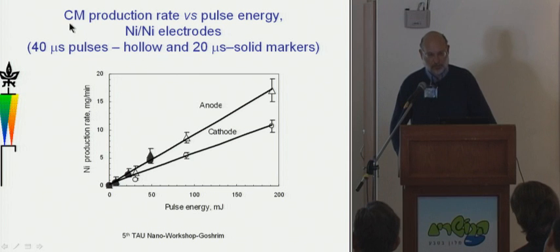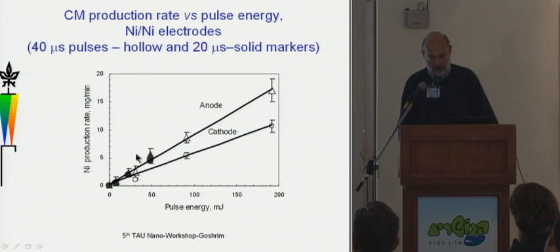This was in the contact mode. It was operating at 100 hertz. And, of course, you can see that with the energy of the pulse, the production rate goes up more or less linearly. No big surprises.